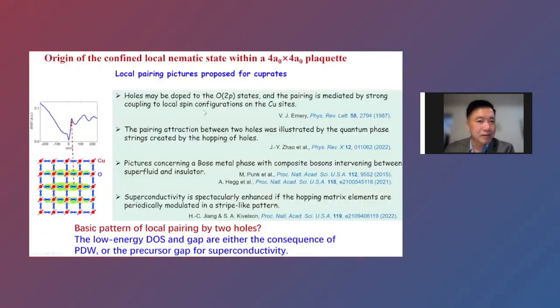This is about why it is nematic within the block. We can find several literatures. Here I mention the first one to you. So Emery, in the early days, said that the holes may be doped to the oxygen state, and the pairing is mediated by strong coupling to the local spin configuration. And our data somehow is quite consistent with this one. But of course, there are other theoretical papers showing that on the underdoped side, it is easy to form this kind of nematic state.